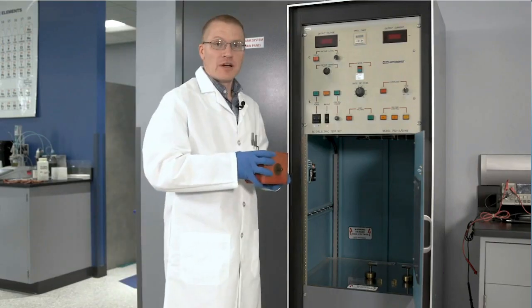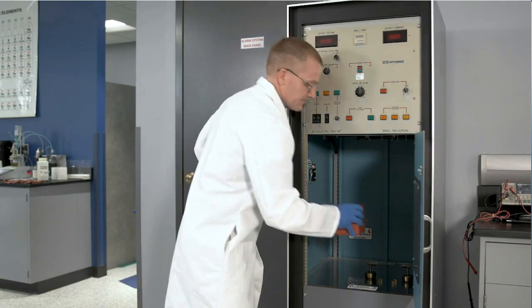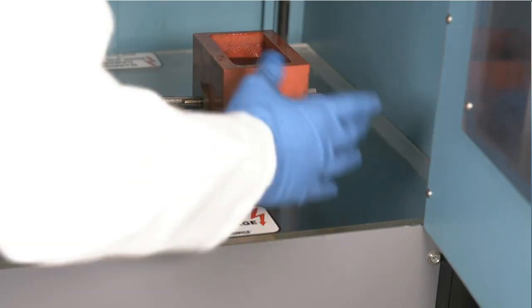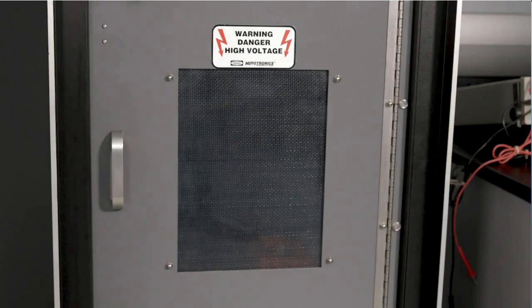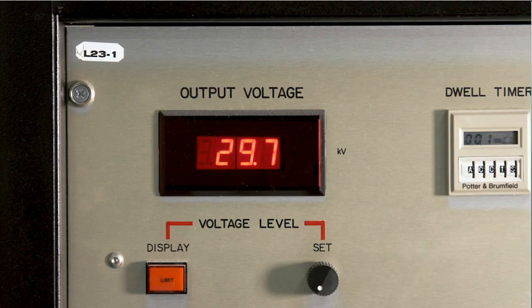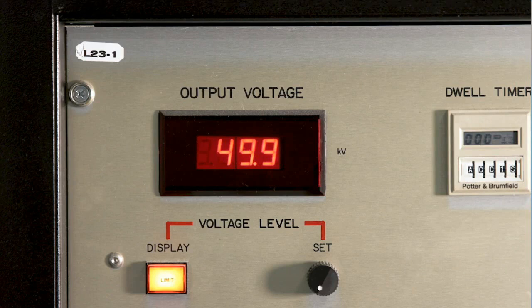Now I'll be conducting a dielectric strength test. And then we'll go ahead and trigger the high voltage, and the voltage between those two electrodes is going to ramp up to 50,000 volts until it arcs through the sample, which measures the dielectric strength of the polymer.